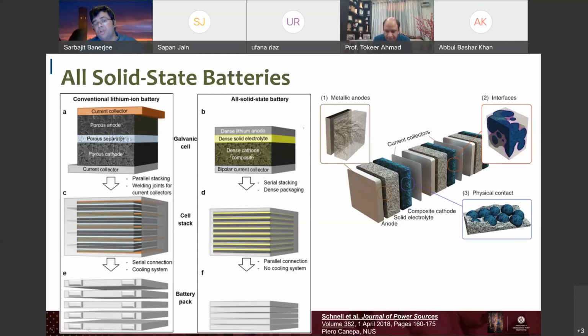if this ends up being true, or if this ends up being scalable, this is an incredibly powerful combination. But the challenge with the system is to use lithium metal anodes. Lithium is incredibly reactive and forms a complex interface with the cathode and with the electrolyte, and there's a lot of interfacial reactions. And then the reversible deposition, the plating and stripping of lithium, tends to result in dendrite formation. And then ultimately, there are a lot of volume changes going on as lithium is being stripped and plated, and this will result in these components, the solid electrolyte and the anode, or the solid electrolyte and the cathode, losing contact.